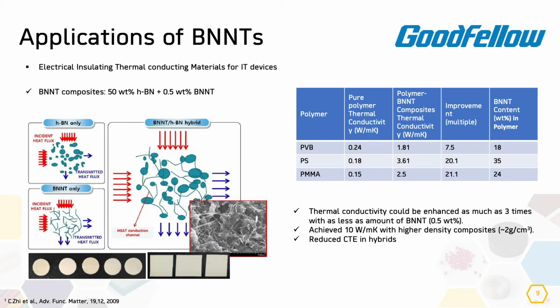For example, our great research group has conducted this project, and we can see that the boron nitride nanotubes composites with 50% weight percentage of hexagonal boron nitride nanoparticles, while with 0.5 weight percentage of boron nitride nanotubes, they can conduct heat better than just the hexagonal boron nitride nanoparticles or just the boron nitride nanotubes. What is happening when you're having the boron nitride nanoparticles and the boron nitride nanotubes is that the nanotubes are working as heat conduction channels.